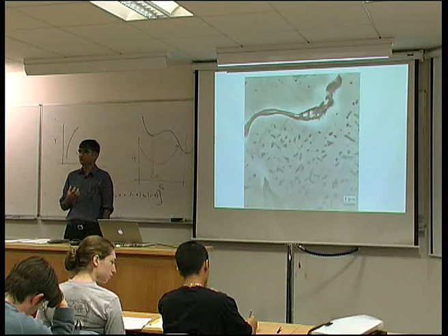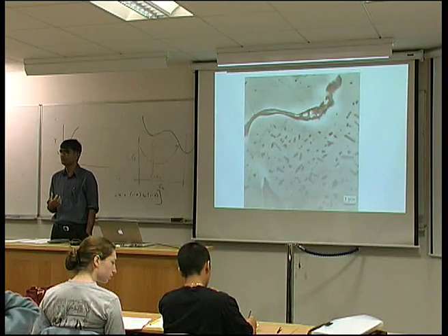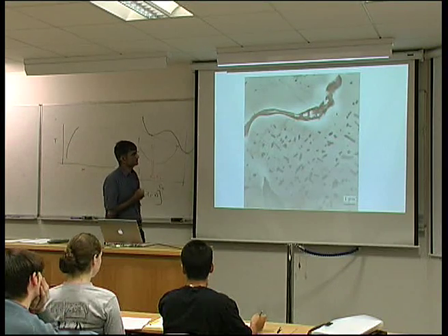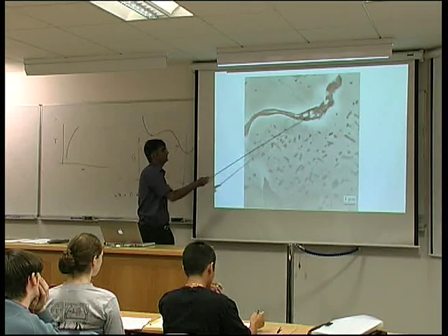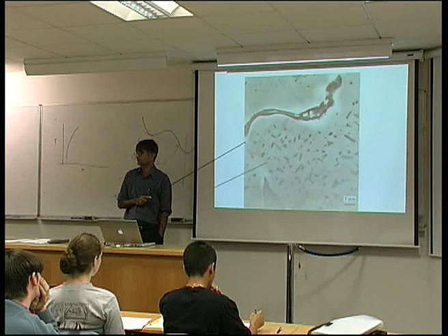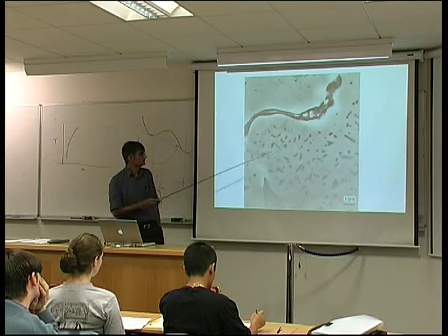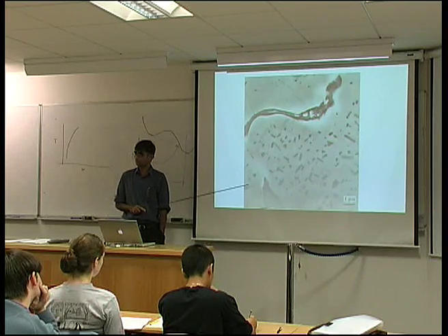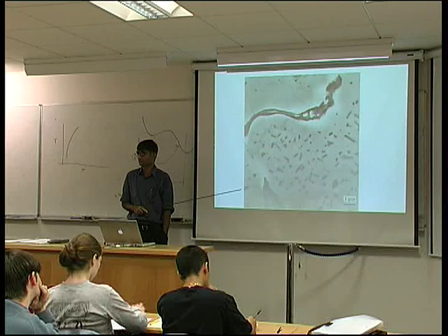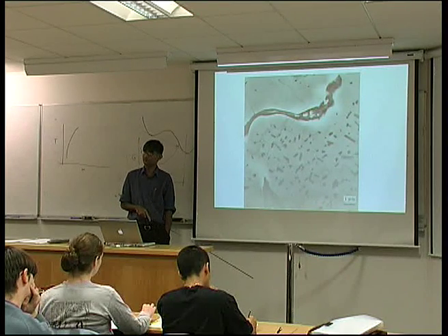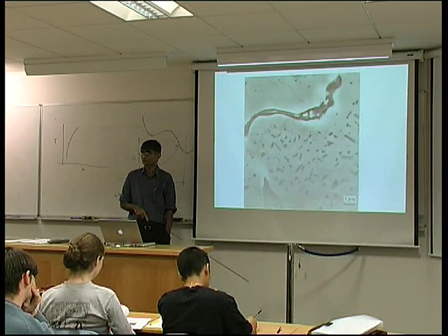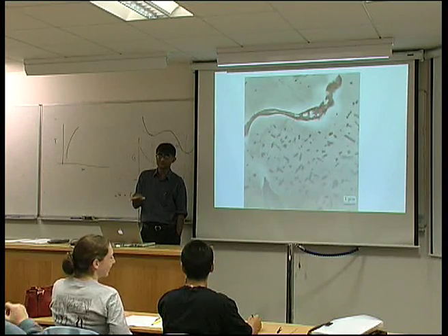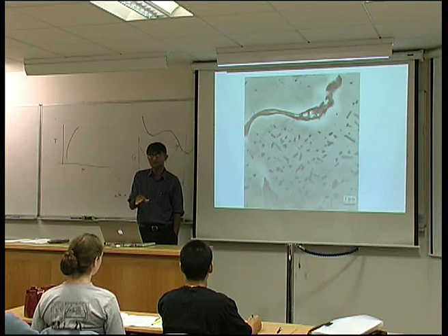there's one problem with precipitation strengthening of aluminium, which is quite an important problem. Now, can you see in this microstructure that here we have a grain boundary between two alpha grains? There is a region here, after heat treatment, which is almost free from precipitates. Okay. And that's what we call a precipitate-free zone. Now, any ideas why we get these zones? Because all of the solute diffuses to the boundary. Yeah.